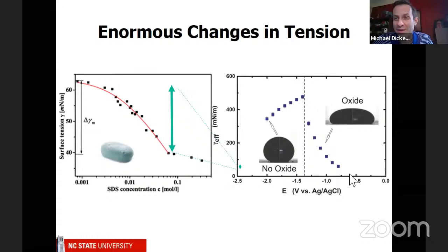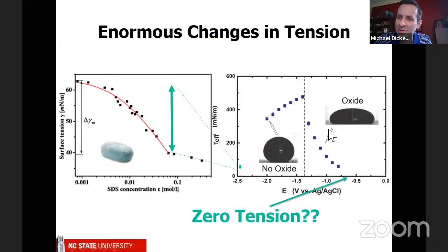Now, if you look at this plot, you should be kind of mad at me a little bit, or maybe mad at my student, because golly, why did they not measure one more data point? Doesn't that look like if it were to go down to here, it should be 0 surface tension? And isn't that interesting? I don't really know of any materials that have 0 surface tension. That's very, very strange, because if something has 0 surface tension, it should basically just mix. So the reason that we don't have a data point there is because the technique we're using doesn't work anymore. So let me show you what happens at that point.